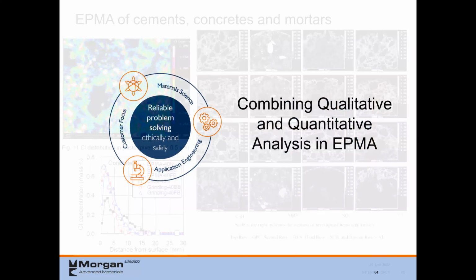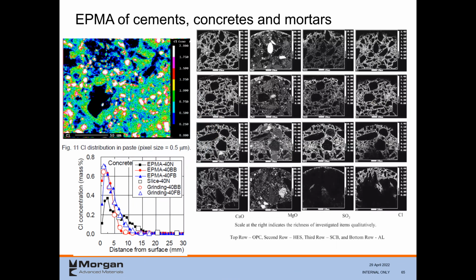Let's see, so here's some combination stuff. This is working with some cement samples. And this was part of a thesis project also, where we did SEM, EDS, WDS, and then brought out some quantitative analysis also in order to get specific compositions to show that this particular cement that they were making, for an application to be used in a space application. So they were able to get the composition that they needed.